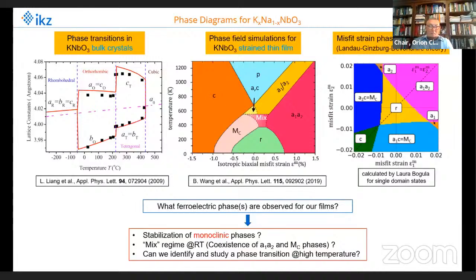For example, close to room temperature, we see a mixture of the monoclinic MC phase and the monoclinic A1, A2 phase. And it would be nice to experimentally prove the existence of these monoclinic phases, in particular to prove the existence of this mixed regime at room temperature. And the other question is, can we identify and study a phase transition at high temperature, and how does this mixed regime change at high temperatures?